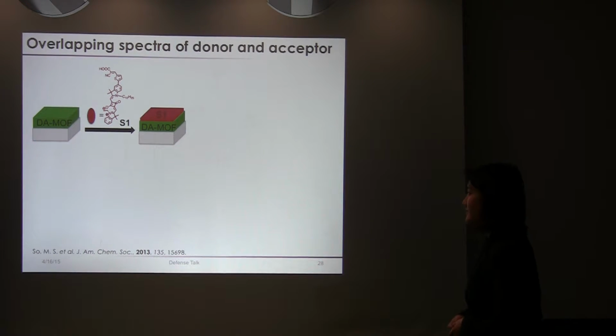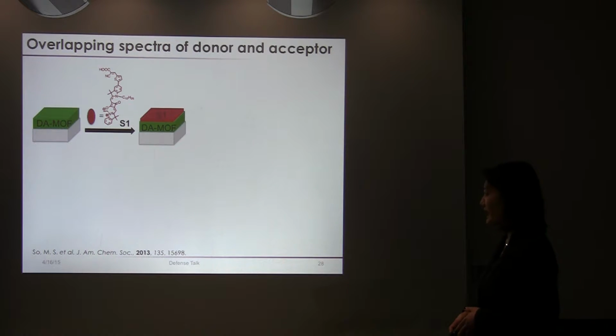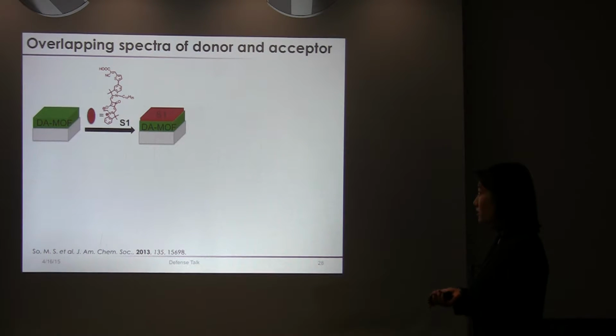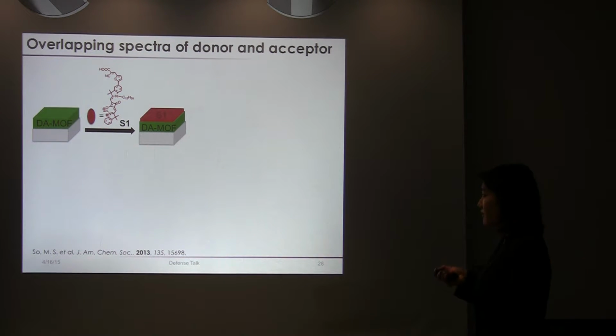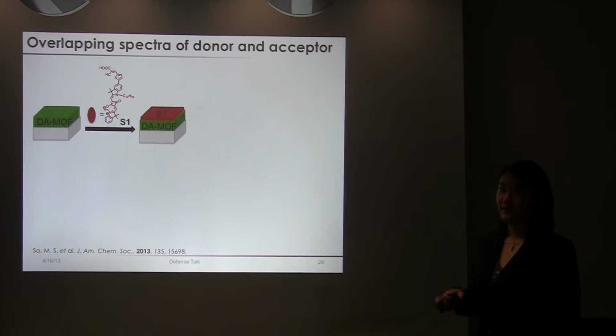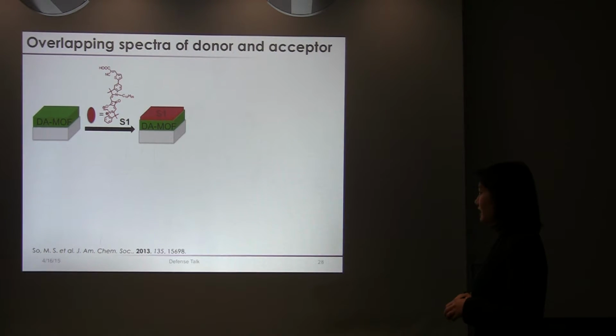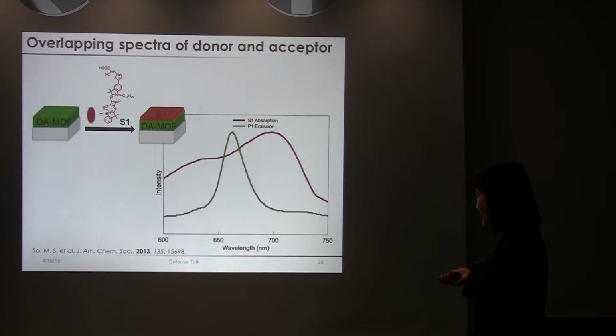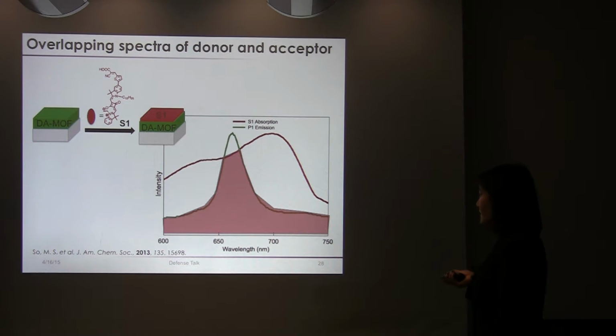Right. So in my group's previous study, since we observed that in a DA MOF, we could see very efficient exciton migration, I reasoned that if I did this in a thin film, I should also be able to see similar phenomena. So what I did was assemble a DA MOF film using layer by layer growth and deposited this far red absorbing S1 dye on the periphery of the DA MOF film. And I chose this candidate because the S1 absorption overlaps very well with the P1 emission. So this sets up one criterion for long-range Förster energy transfer.